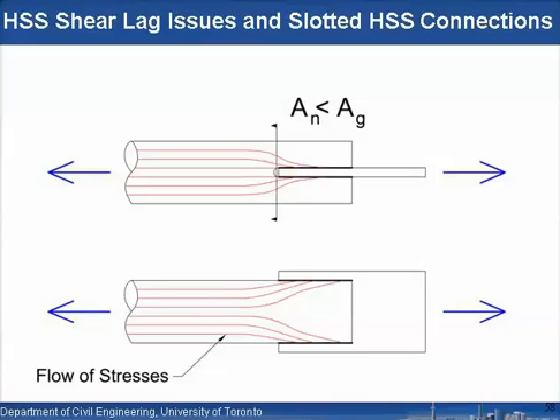Well, when this is done, the tube is usually over-slotted, which means the slot is made slightly longer than the insertion length of the plate, which means you'll have a small gap at the end here. So there will actually be a hole at the end of this connection. That's right at the very, very critical place where your connection is likely to fail. And you've reduced the cross-sectional area from a gross area down to a net area.